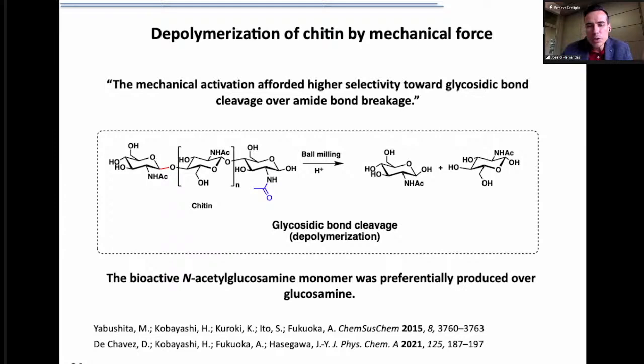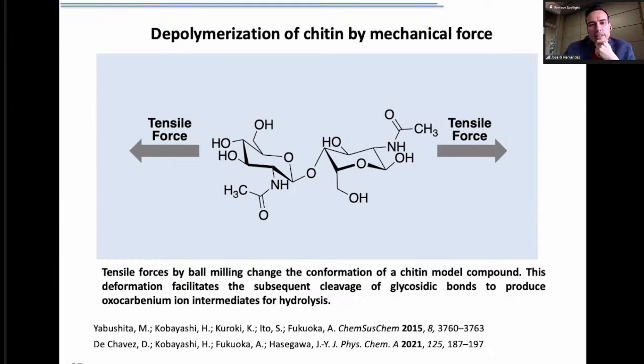So there were some computational studies that were carried out trying to understand what was going on. How was the force promoting that change in selectivity? What they found was that if you have a model compound that simulates chitin and you apply tensile forces, well, those tensile forces promote changes in the conformation of that polymer and also facilitate the cleavage of the glycosidic bonds. So the tensile force really plays a role in facilitating the reaction that cleaves the backbone of the polymer. But because directionality was not applied, or is not so effectively applied, through the amide bond, the deacetylation was not promoted so easily.